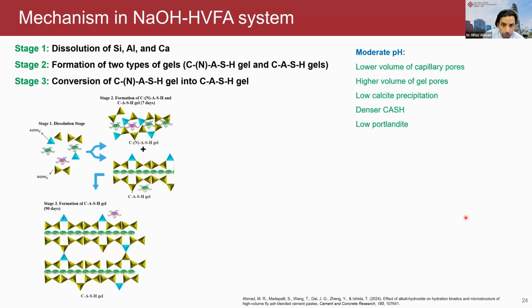So we again studied different durations. For example, what happened at 7 days or at very early age, what happened at 28 days, or what happened in the long term. What we observe is that there are 3 different mechanisms which evolve. First of all is the dissolution when we mix this sodium hydroxide with fly ash. There is a tremendous reaction going on, and there is a significant release of silica and alumina species.